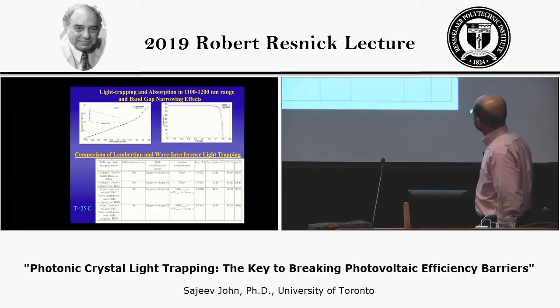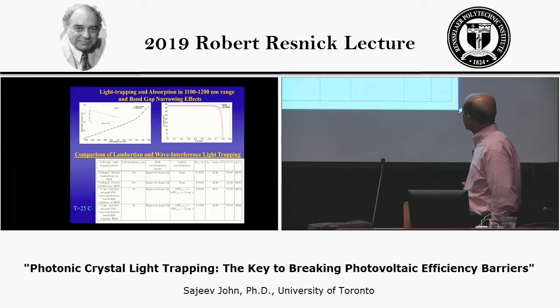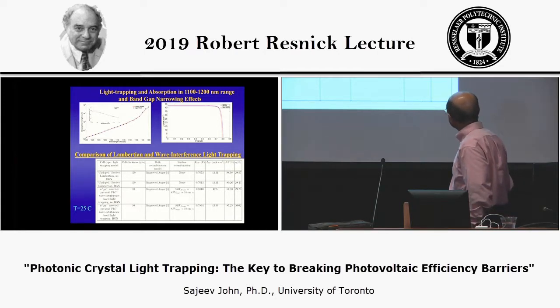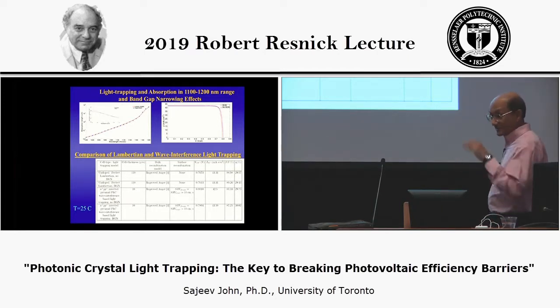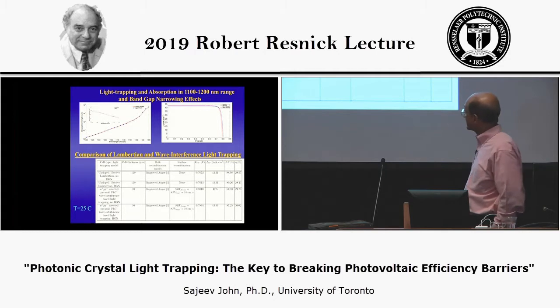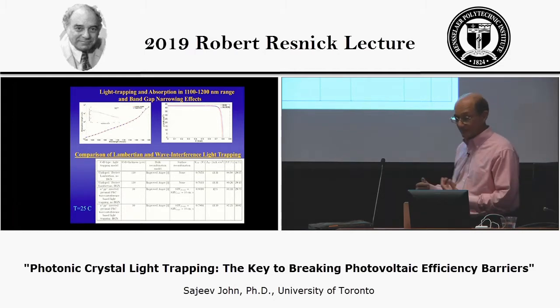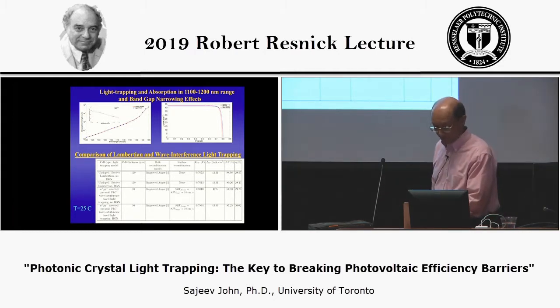wavelength regime. The voltage does go down a little bit, but it turns out that that actually improves the efficiency a little bit. In this case, with this top contact cell, it showed an efficiency theoretically of slightly over 30%, using the recombination models that are provided by the Fraunhofer Institute to us based on experimental data.